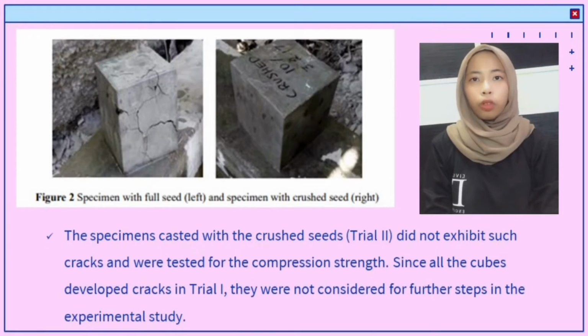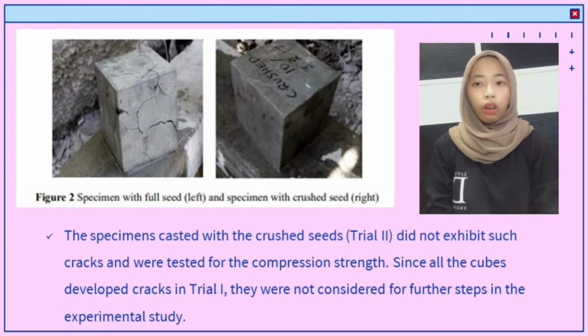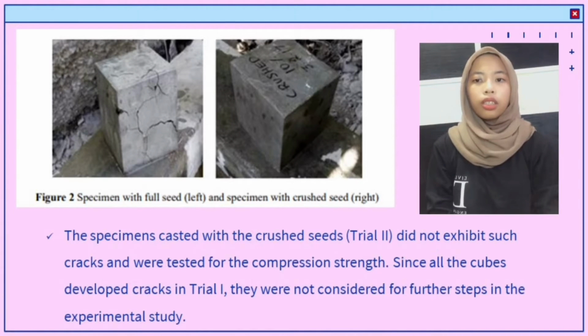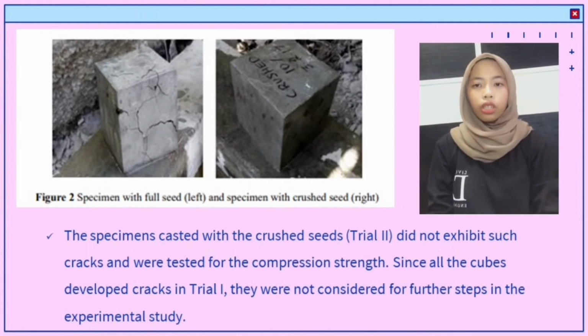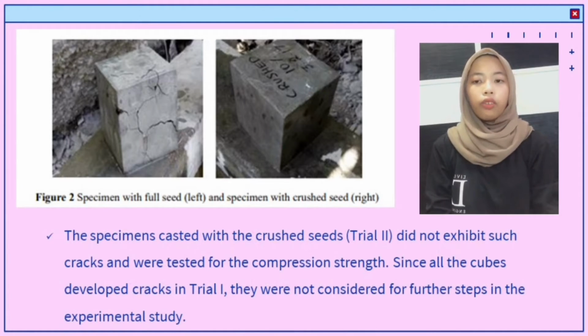So, before we move to the findings and the results, we must know the problems encountered during the methodology. On the 7th day of curing, when the specimens were taken out from the curing tank, it was found that the trial 1 specimen, which is seed used without crushing, developed cracks on drying. The cracks were very intensive, and it was observed that the cracks started to develop at the junction where the seeds were present in the concrete mixture. It was important to note that the full seed did not have the tendency to bind with the concrete mixture.